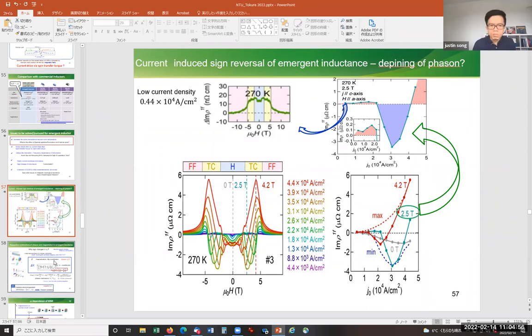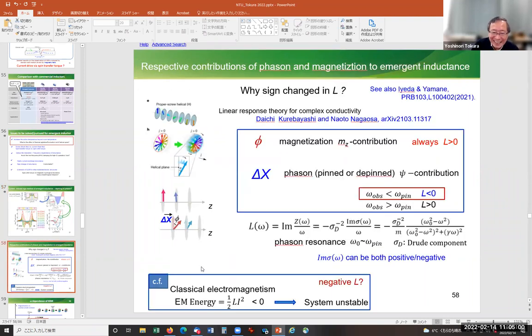Oh, and we anticipate, sorry, we anticipate that this kind of phason motion has some resonance frequencies. So around this resonance frequency, the inductance value is changing sign. So maybe the control of the spin phason frequency, the phason motion, is the most important. It's originally the Nambu-Goldstone mode, so we have to pin it down. So in that case, the phason contribution disappears, and only the positive component survives. As compared with the phason its magnitude might be small, but it can be extended to the higher frequency. It might be good news for the application. Yeah. It's very interesting. Thank you very much.